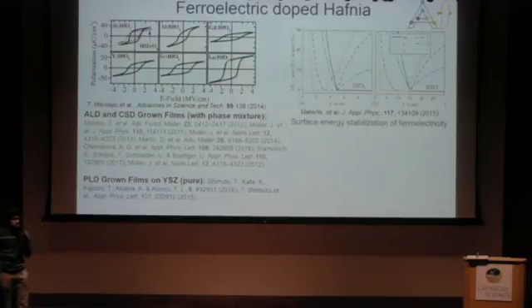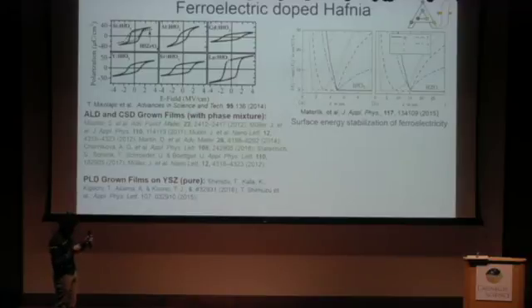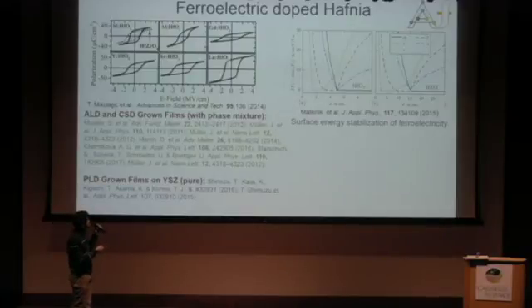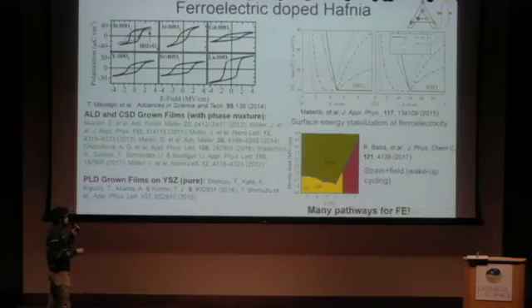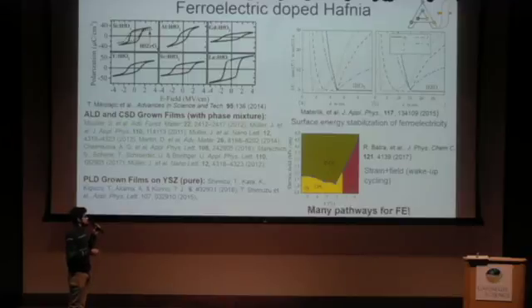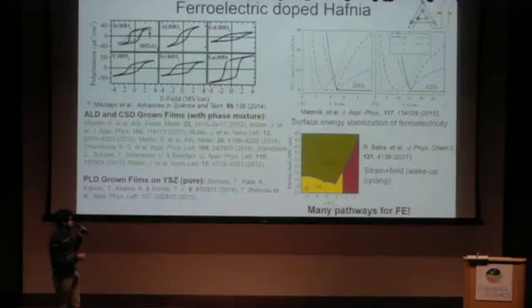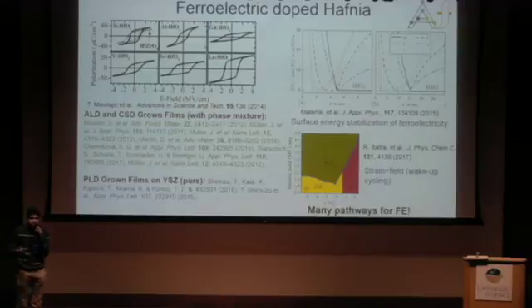Insights, as always, come from theory as to what stabilizes this polar orthorhombic phase. And here, for instance, in this paper from Munich, they consider the surface energy of these small nanoparticles to be a stabilizing factor for this polar orthorhombic phase, and they determine, for example, this red curve gives the energy stability of the ferroelectric phase, and it is stable in certain size ranges depending on the composition of the material that they're looking at. Similarly, this group from the University of Connecticut suggests that you could go to a polar orthorhombic phase by applying biaxial compression as well as an electric field. So it looks like there are many pathways to get to this ferroelectric phase.